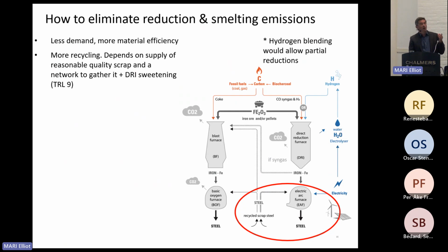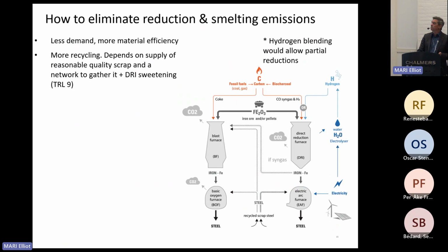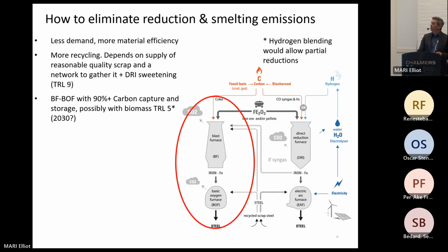More recycling. Recycling is limited by the amount of scrap that's available and high quality scrap. If the scrap gets contaminated, especially with copper, all it's really good for is rebar. You need really low copper levels and selenium levels, I believe, in order to make really thin sheet steel. And again, you can add a little bit of extra new DRI briquettes to it to get below the contamination levels. And that's something that can be done today.